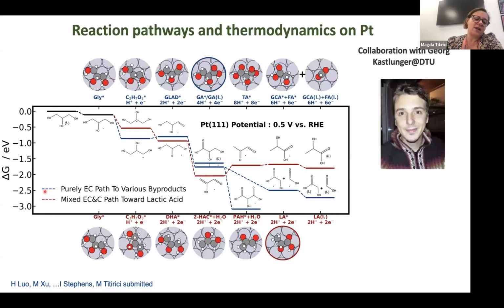If you do some energetics, so you look at the Gibbs free energy of all these different intermediates and how they would absorb on platinum 111, you would see that you would have the path in blue, and these are the energetics for pure electrochemical, and the path in red, which is actually a mixture of electrochemical and chemical pathway.